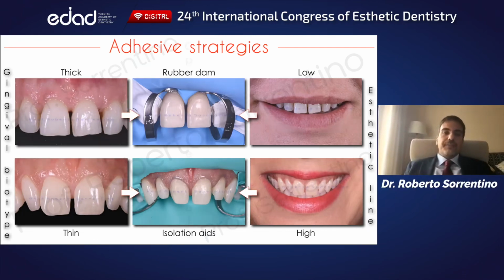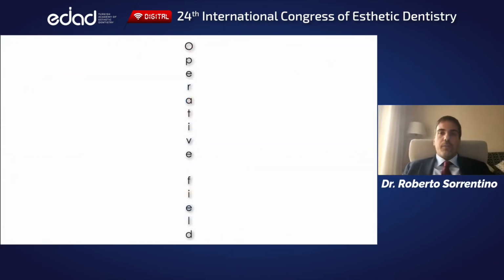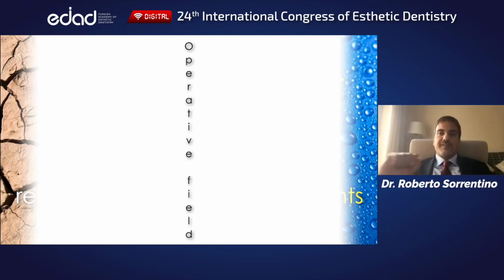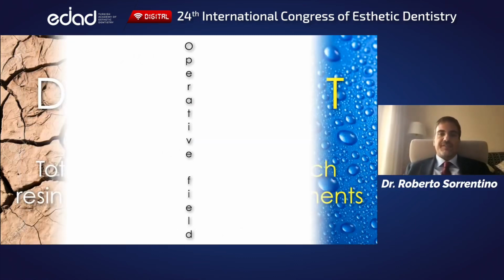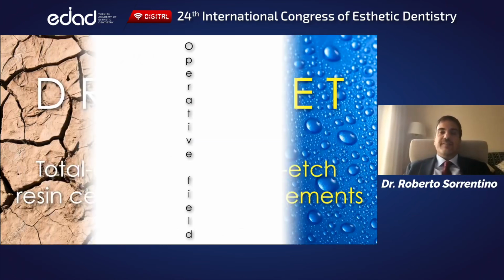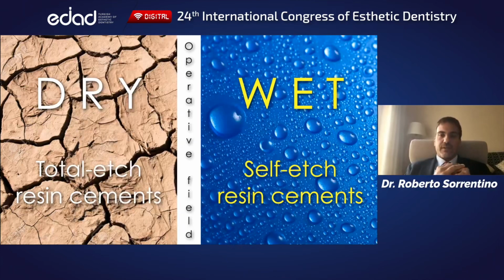Finally, the selection of resin luting agents has to take into account the moisture content of the operative field. If it can be kept dry, total etch resin cements still represent the gold standard, particularly in the presence of enamel and in anterior areas, to prevent microleakage and peripheral staining. Conversely, in the presence of residual humidity and onto dentin, self-adhesive cements should be considered the first choice materials.